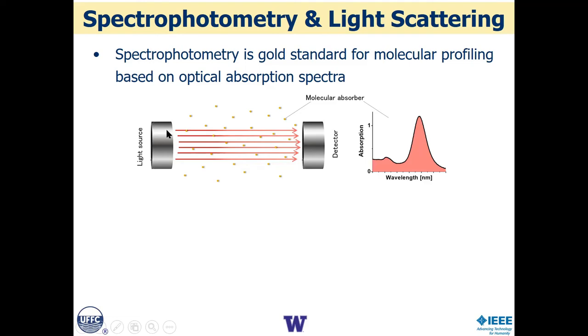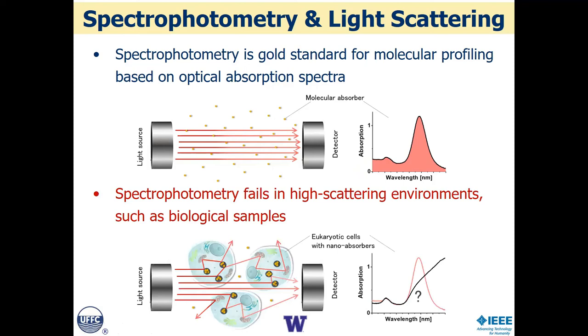So let's consider a simple experiment to explain it. Consider that you want to profile these little nanoparticles in a solution. You have a light source and a detector, and you do a simple substitution measurement. That's what spectrophotometry is. You measure the light from source to detector without the solution in there. You put in the solution, and you measure how much light is lost. That gives you the absorption. From that, you sweep the wavelength, and so you can get the optical absorption spectra, which is directly related to the molecular characteristics of those contrast agents.